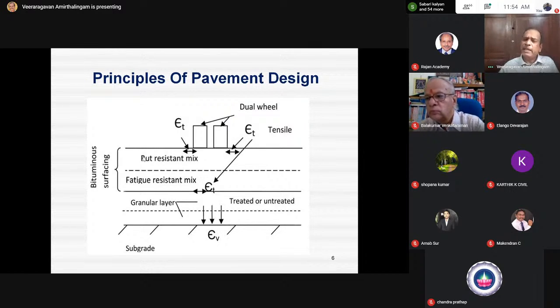Third, many of the pavements constructed in India prematurely crack. So once you find a crack at the top, it does not mean that it is a fatigue crack. This is a top-down crack. Top-down crack causes are different, but unfortunately, we do not consider top-down cracking as a criteria in the design process. I do not know why. I think that should also be considered. That is related to the binder that you use, mix that you adopt, overloading, tire pressure, temperature, and other climatic factors.